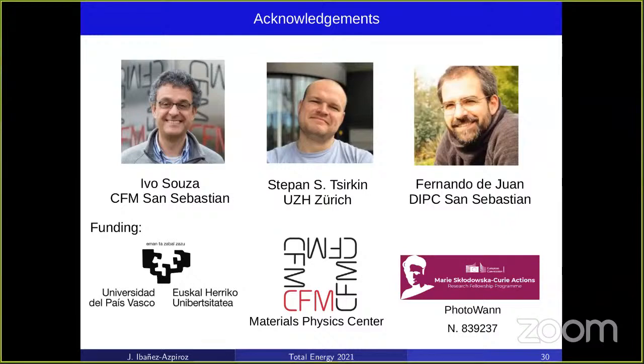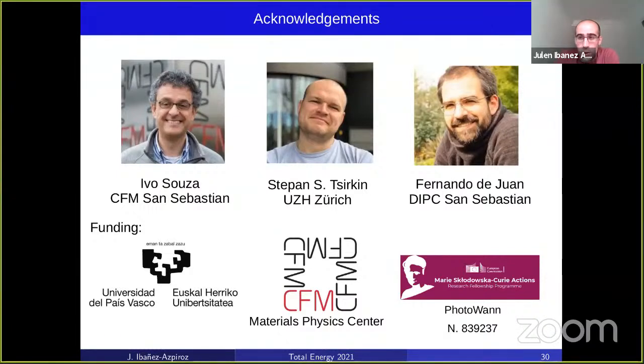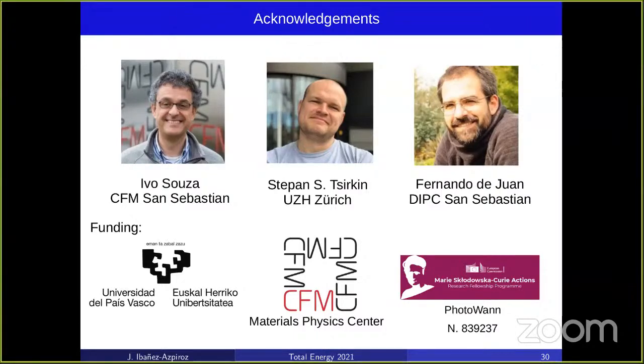Oh, okay, thank you. And how about the scissor shift? Since we are dealing with semiconductors, we might need an accurate gap to have a good spectrum of the shift current. Totally true. The good thing is that the shift current matrix elements, and the whole conductivity, are invariant under the scissor shift. It will just shift the calculated spectrum, usually to higher energies, but the profile of the spectrum would be the same. It's invariant. Oh, I see. Thank you so much.